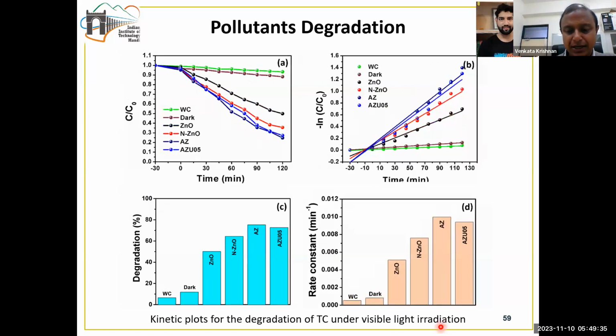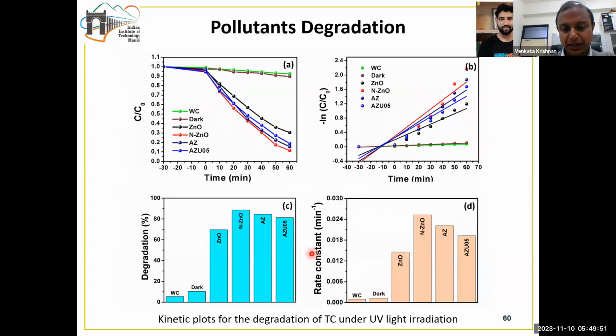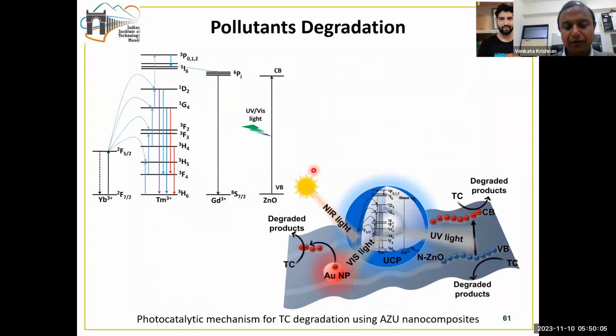Then we did the same reaction under visible light irradiation, and here it's the gold nanoparticle and its SPR effect which is playing the major role. And we could clearly see that the AZ is exhibiting the best photocatalytic activity among all these samples. Then we also did the same reaction under UV light irradiation, which indicated the N-ZnO playing the major role and showing the best photocatalytic activity, which is also expected because this is a UV active material and it should show good photocatalytic activity. And finally, we deciphered the mechanism of the reaction.